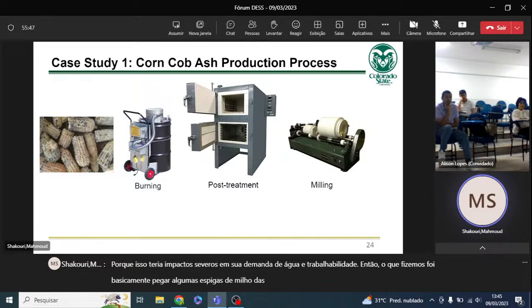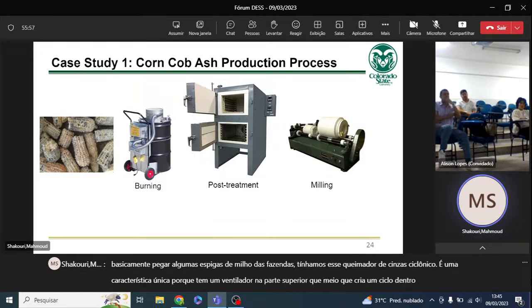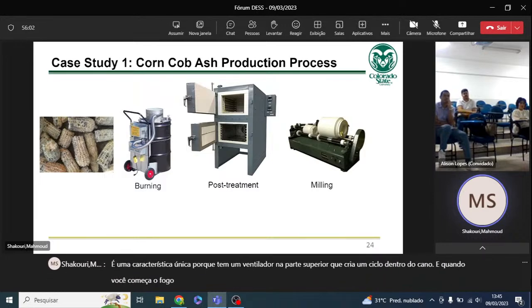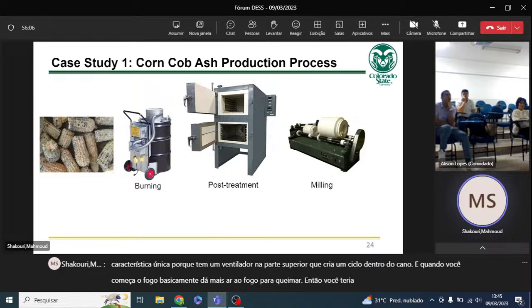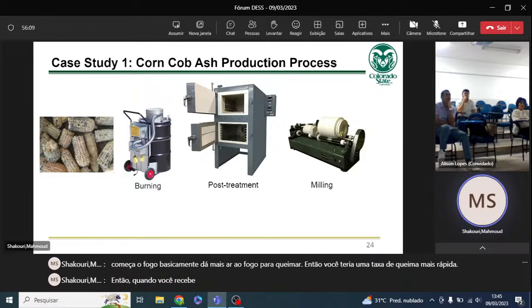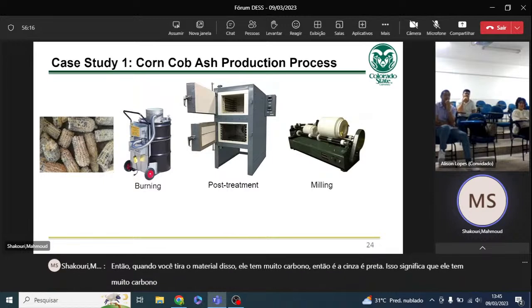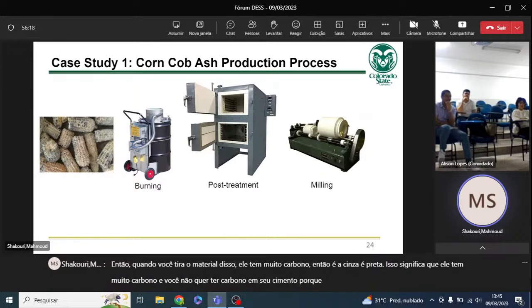We had this cyclonic ash burner. It's a unique feature because it has a fan on the top that creates a cyclone inside the barrel, and when you start the fire, it basically gives more air to the fire to burn. So you would have a faster burning rate. When you get the material out of this, it has a lot of carbon. So the ash is black. That means that it has a lot of carbon, and you don't want to have carbon in your cement because it has a negative impact on your properties.